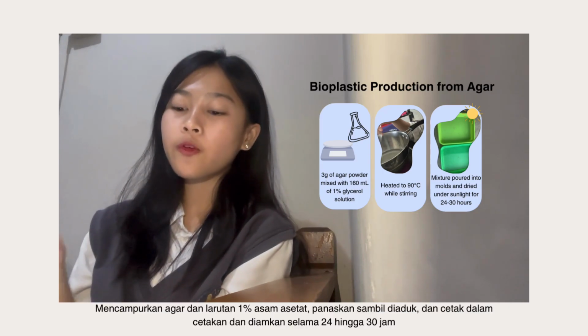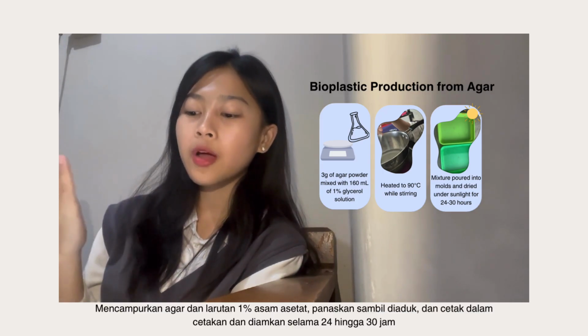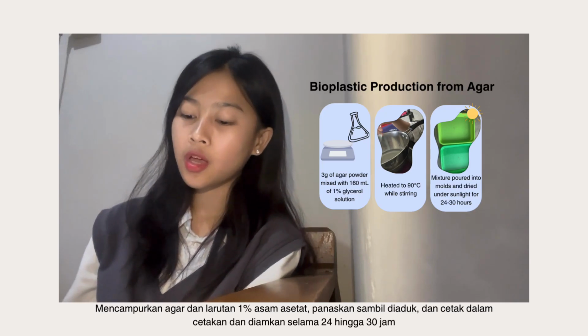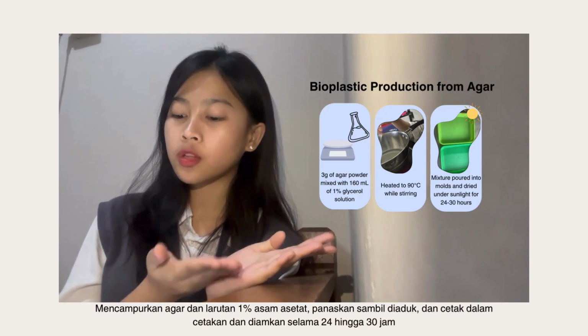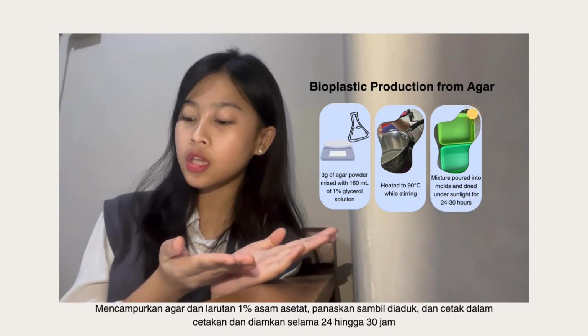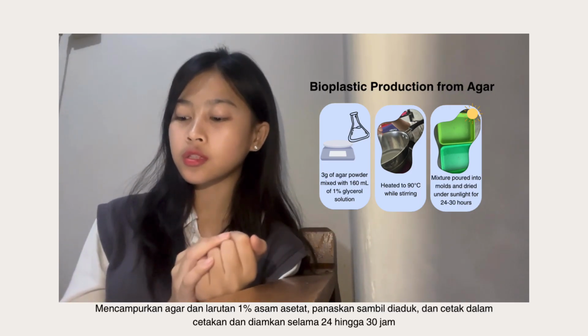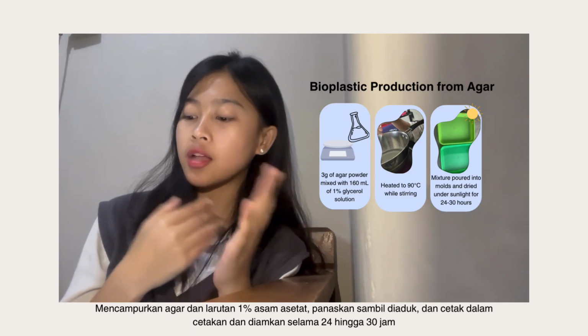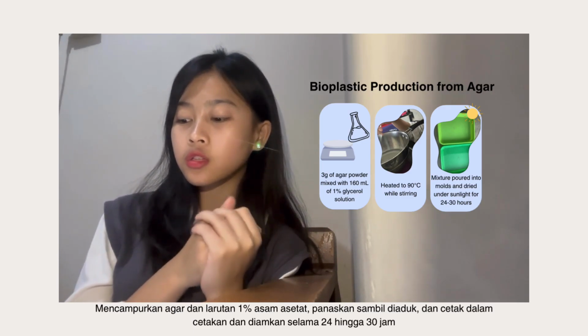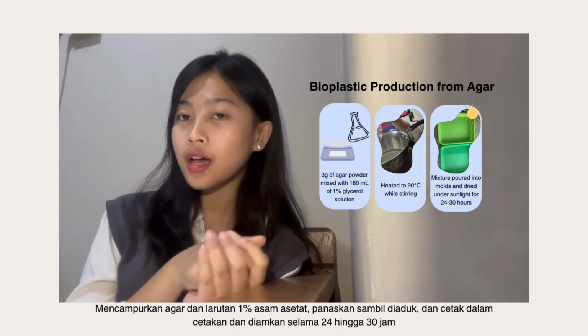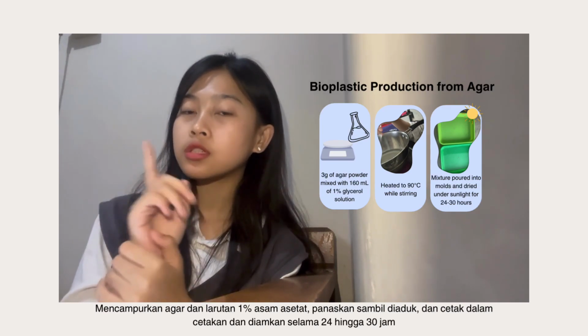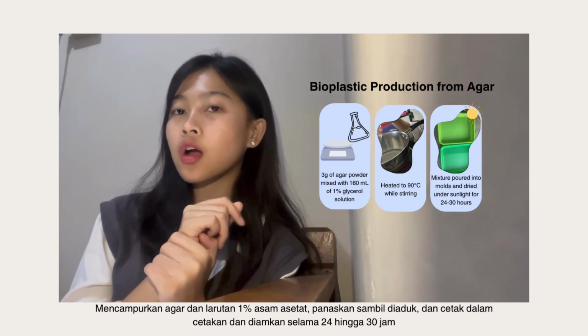The first step for the methodology is bioplastic production from agar. Agar powder is mixed with 1% glycerol solution and heated to 90 degrees Celsius while stirring. And then the mixture is poured into molds and dried under the sunlight for 24 to 30 hours.